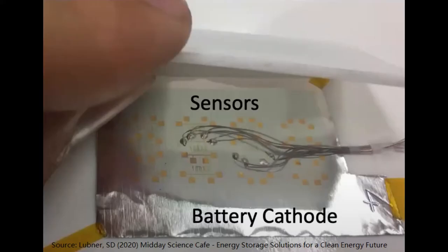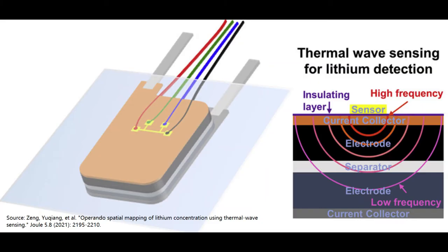Yeah. So I briefly mentioned, at a high level, how these measurements work. You've got a sensor, you apply periodic heating at the surface, which creates a thermal wave that will then diffuse down into your substrate, which in this case was a battery. What's particularly favorable is that the depth to which that heat diffuses depends on the frequency of your wave. So even though your sensor lives on the outside, you can control how far into the battery you're looking by controlling the frequency of the wave that you're sending into the battery.